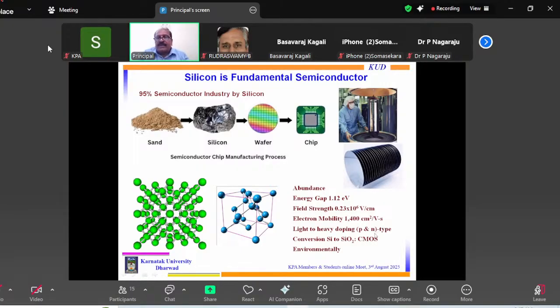Light to heavy doping is a very important aspect. For any semiconductor, if we want to put it to any application, we should be able to dope it and convert it to P and N type. More importantly, you should be able to control the doping level. That is well done in the case of silicon and germanium, but silicon is much more. You can have N minus or P minus doping, you can have N or P doping, and you can have very heavy doping, that is N plus and P plus. It is really wonderful because for any semiconductor you discover, you have to have this control.